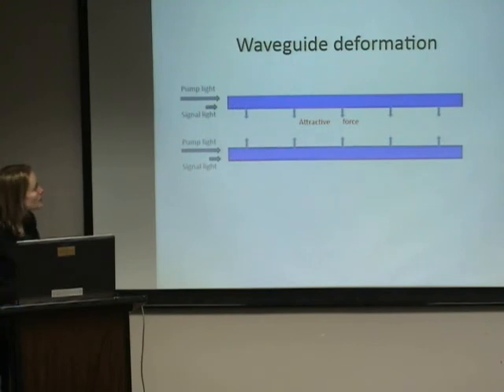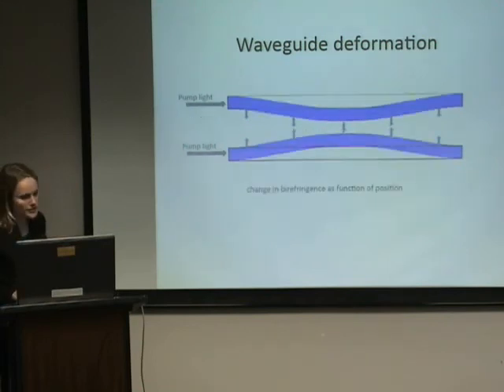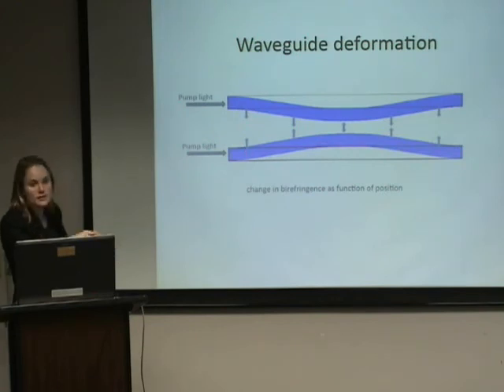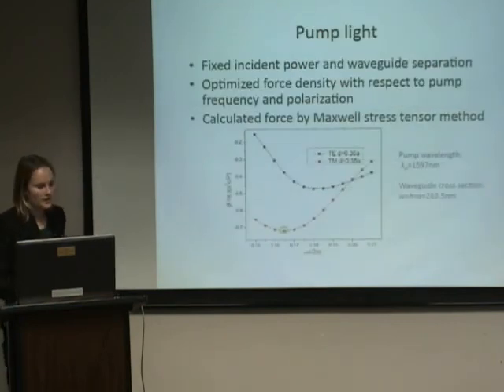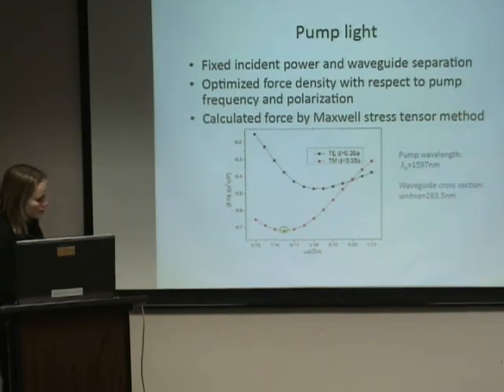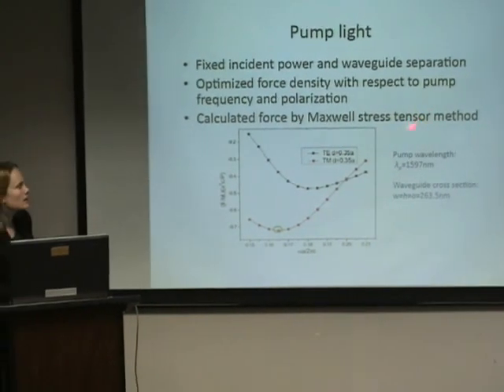I'm going to skip a few slides here. So what we do then is we consider what happens if you put the pump light in. You'll get a force. They'll deform. And now, as you go along the waveguide, you get a different birefringence, where again, birefringence is a reflection of the difference in how one polarization propagates and the other polarization. And so for a given strong pump signal, we go and we calculate what the force is using the Maxwell stress tensor method, and then we do finite, that'll come next.